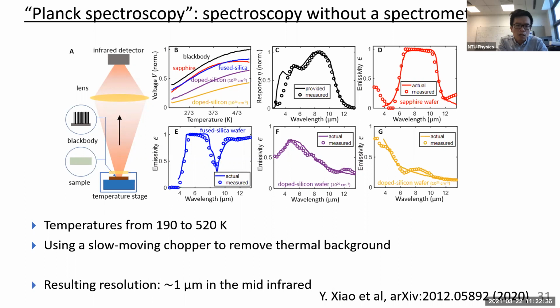I see. Right. So essentially, when we get down below this temperature, the MCT detector that we have in the lab just isn't picking very much up anymore. That's kind of our limitation. In principle, you could go up to very high temperatures. You can imagine going up to thousands of degrees, and doing measurements at much shorter wavelengths, because of course you're getting a lot more signal at shorter wavelengths if you go to very high temperatures. We don't want to melt any samples, and also the bigger your range of temperatures, the more likely it is that your emissivity actually starts changing as a function of temperature.